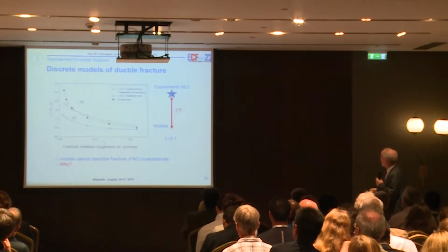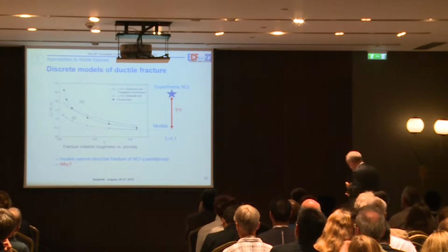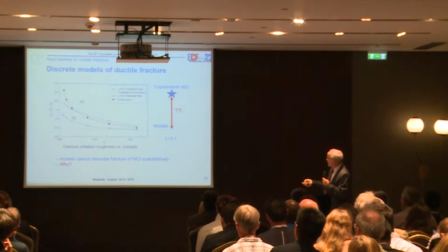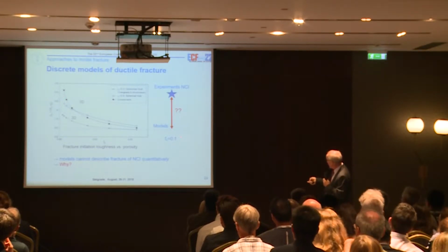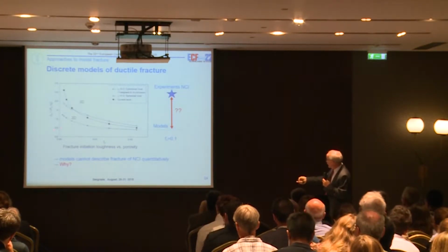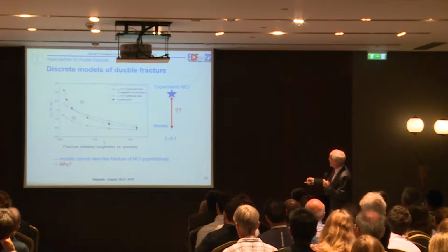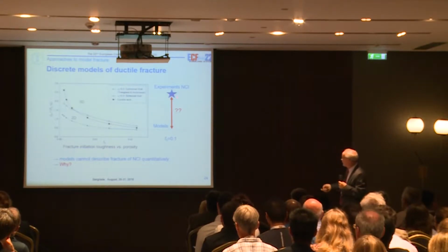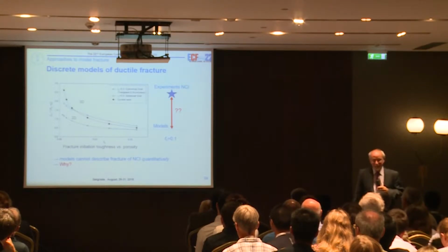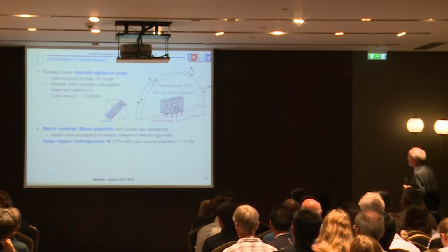So now the question was, the simulations up to now predicted for large porosity, here we have porosity of 0.1 or more, about 0.5 for the parameter C, and experiments showed 2.5. And this was a great challenge. We want to find the answer for it.